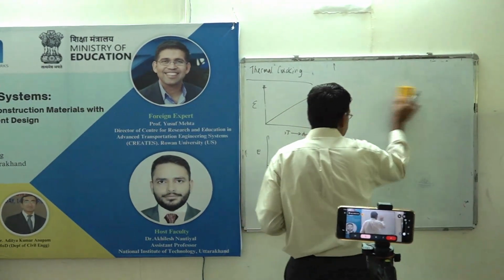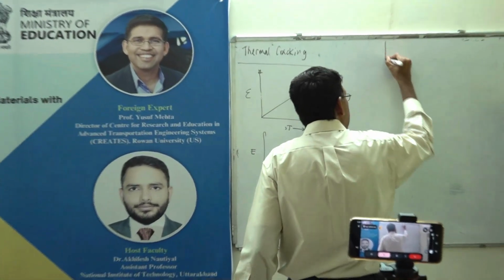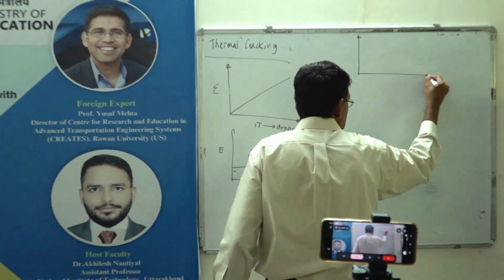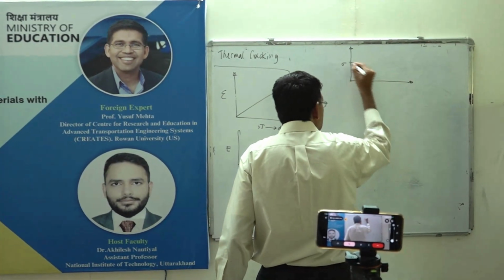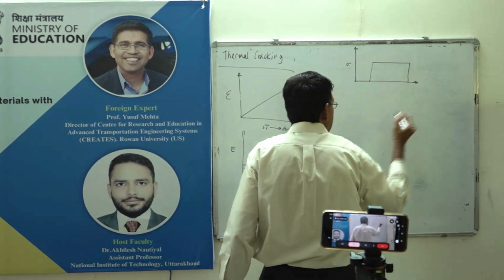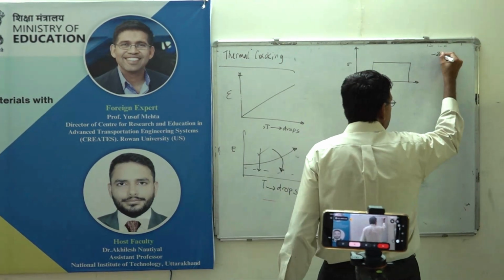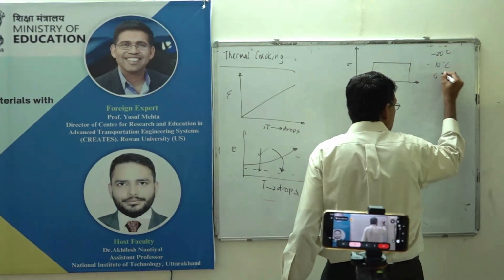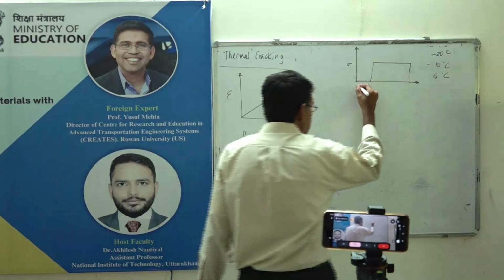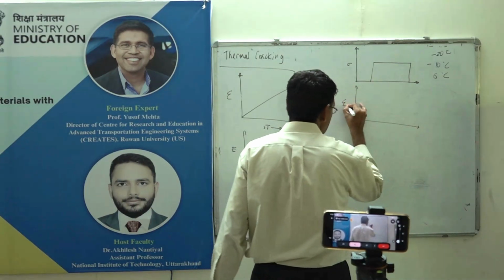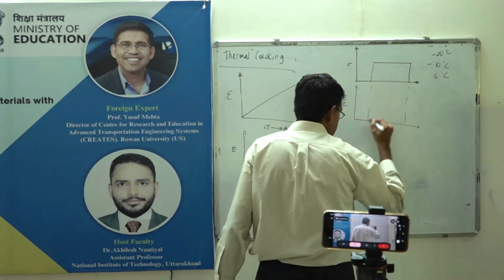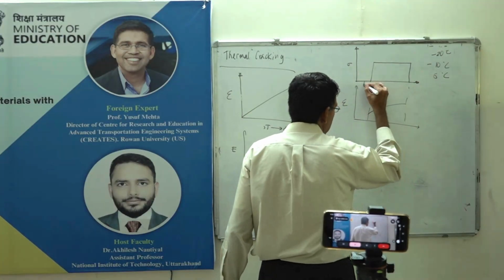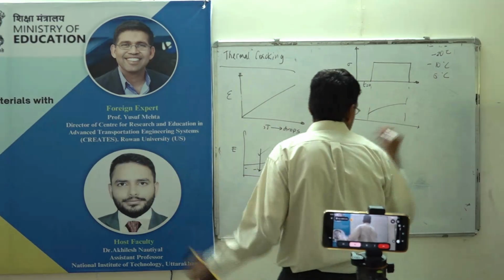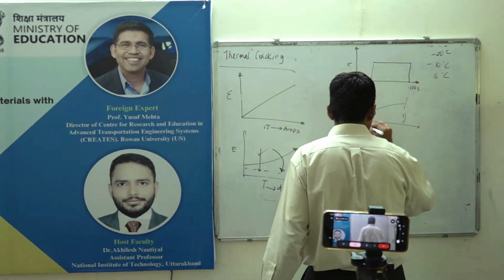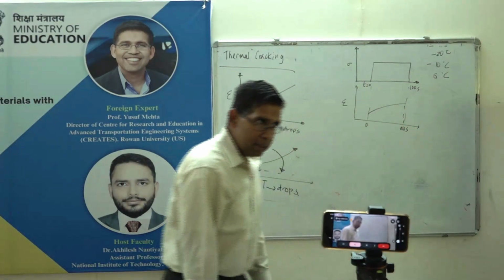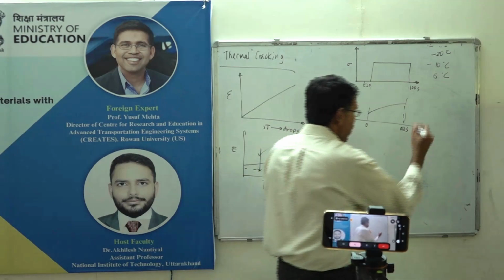Let's look at this. What you do is, you take a load, you apply it for a certain time, right? It's very cold temperature, right? We already discussed this, minus 20 Celsius, minus 10 Celsius, and 0 Celsius, correct? And then you measure strain, right? Again, very indirect tensile strain, and it's going to go something like that. Because over time, this is time equal to 0. I forget how many seconds, 100 seconds, right there. Fair enough? Right? It creeps, you have this, and you have something called compliance.